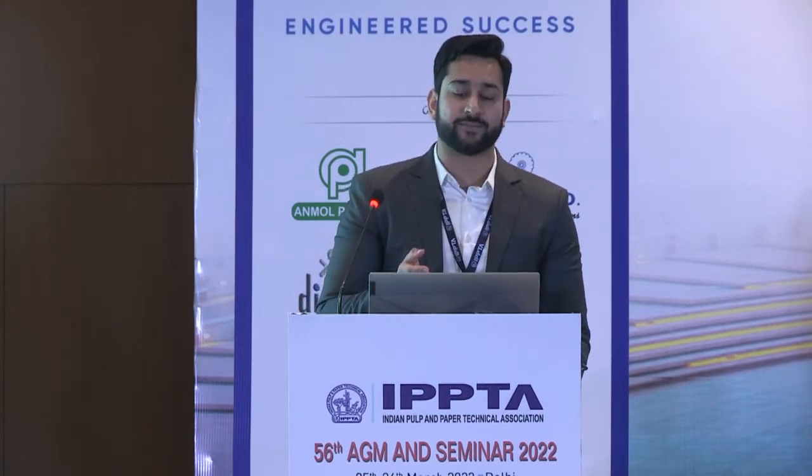And so we have collaborated with a research-based company to introduce micro-encapsulated biocides. The actives which are encapsulated are a mixture of synthetic and natural biocides to effectively prevent odor developing on storage. This microencapsulation is a patented technology, and the microcapsules size from 5 to 20 microns and are delivered in a water-dilutable slurry. The outer shell of the capsule is made of a thermosetting polymer which is heat stable up to 275 degrees, and the core contains the actives.